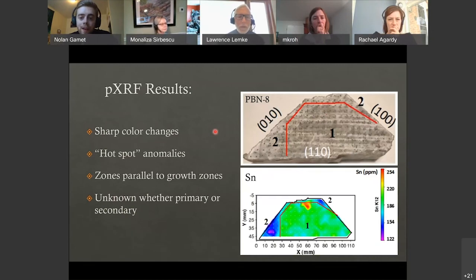So based on these results, we were able to distinguish two distinct zones. First, we looked at the hand sample. You could see a distinct coloration of white on this outer rim, which we called zone 2, and zone 1, which is more dark and gemmy colored.